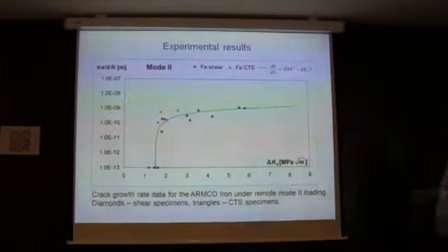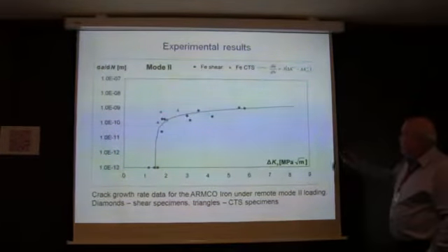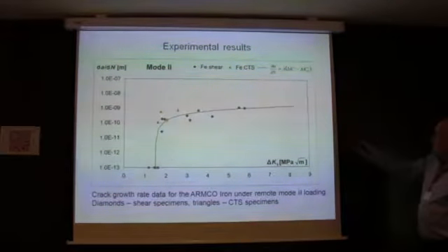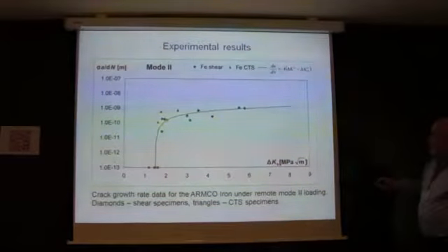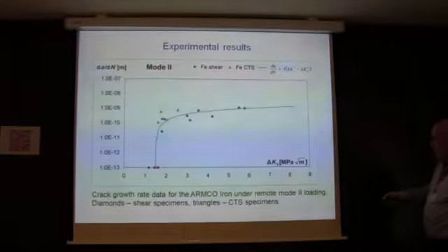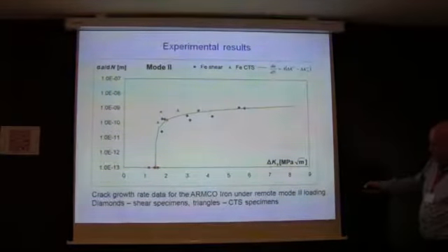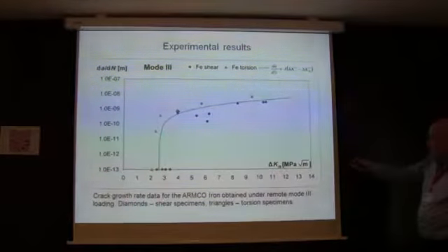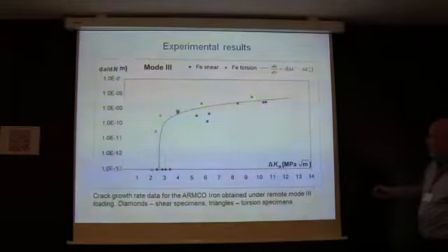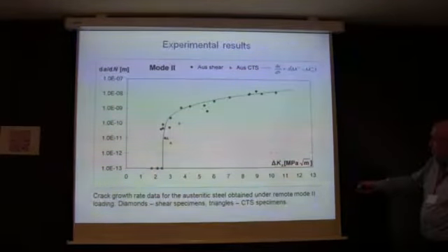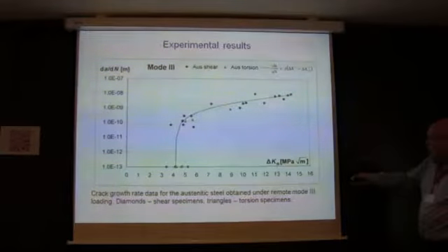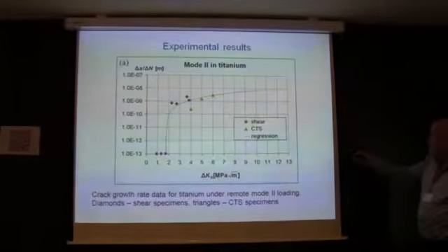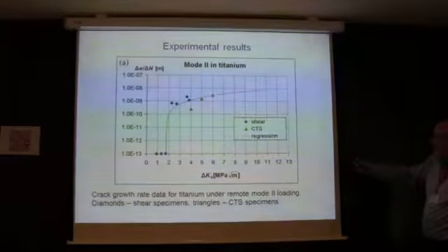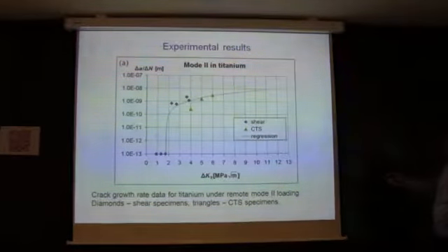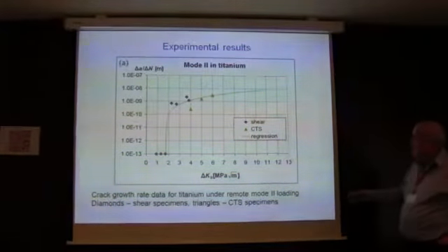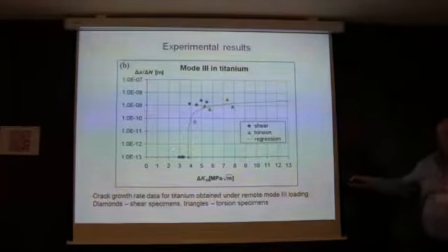These are the results. So you have here two different specimens, CTS specimens and so-called pure shear specimens, and these are the results. So this is mode 2 for alpha iron. This is more or less the threshold value, like this. This is mode 3. You see the threshold value is higher. This is mode 2 in austenite. Again, mode 2 threshold value. This is mode 3, threshold value again higher. This is a new result. This is titanium. Sorry for a few points, but you can see the threshold more or less like this in mode 2, and this is mode 3, higher.